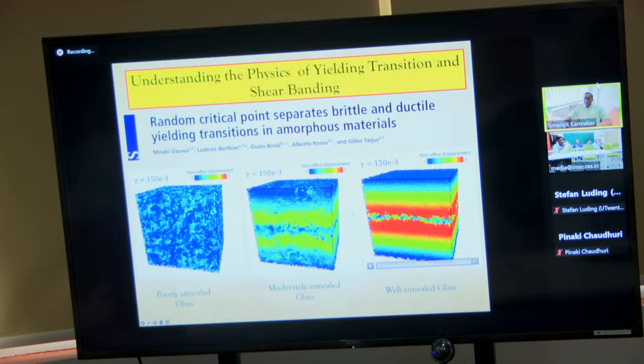And you see that the plasticity, which is color coded using the non-affine displacement, which I'm not going into details of, is very different. Particularly in the poorly annealed glass, you see that plasticity is happening everywhere, and it's a kind of homogeneous yielding process. In a moderately annealed glass, there is some signature of localization of plasticity, but in a well annealed glass, you see a very, very clean localization of plasticity. And this is what is the shear band.